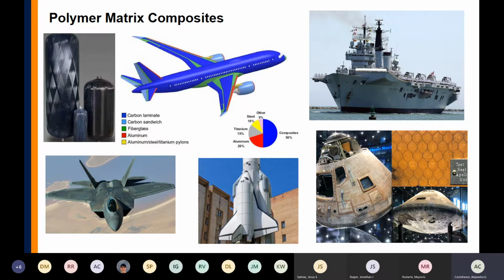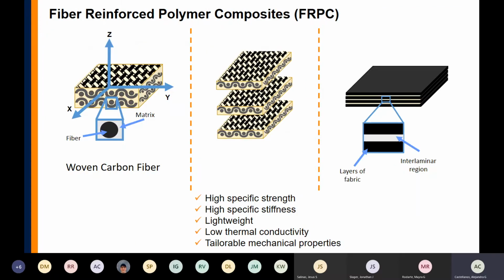So what is a polymer matrix composite? Well, a polymer matrix composite is basically fibers that are reinforced in a polymer matrix. All these layers are stacked up or layered up to create a laminate. One of the challenges that we still have in composite materials is the in-plane mechanical properties, which means where we have the fibers, which will be the Y and the X direction. Those mechanical properties are really good, really strong, very stiff.